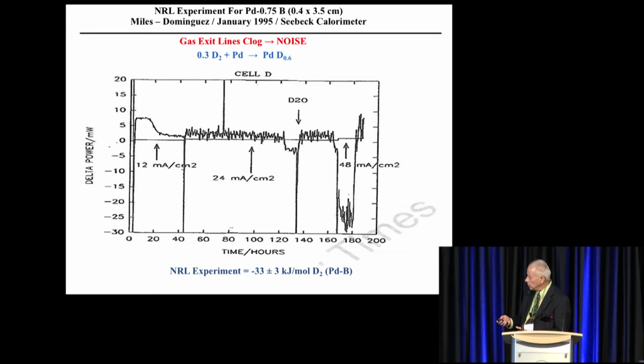And you see when they started the experiment, there is excess heat due to loading. Well, I calculated that by integrating under the curve, and I gave it minus 33, plus or minus 3. So palladium-boron gives you about the same loading enthalpy effect as palladium. But I had to go back to China Lake, and I didn't really see how they designed everything at the end, but they had the gas exit lines going horizontal.